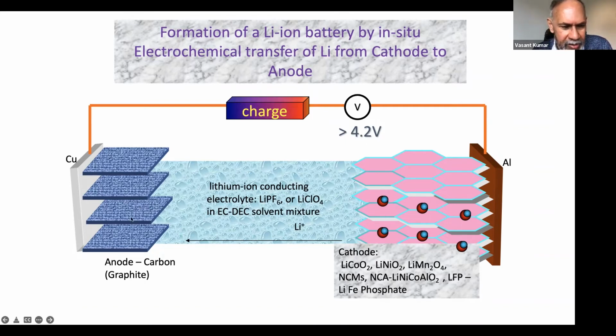And the anode is basically carbon. It's graphite, and it can actually intercalate lithium, for example. Our cathode is again materials such as lithium cobalt oxide, lithium nickel oxide, manganese spinel, or a combination of nickel, cobalt, and manganese, or nickel, cobalt, and aluminum, sometimes known as NCA. And LFP is lithium iron phosphate. So these are the possible cathodes, and all are being used or developed rapidly.